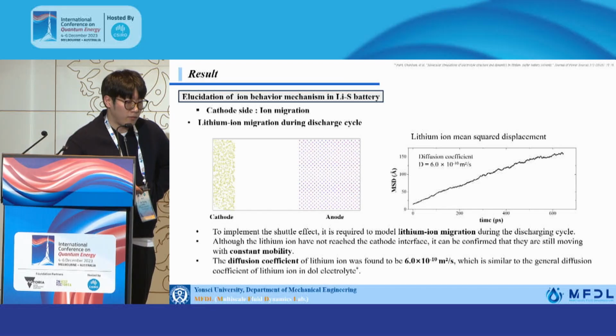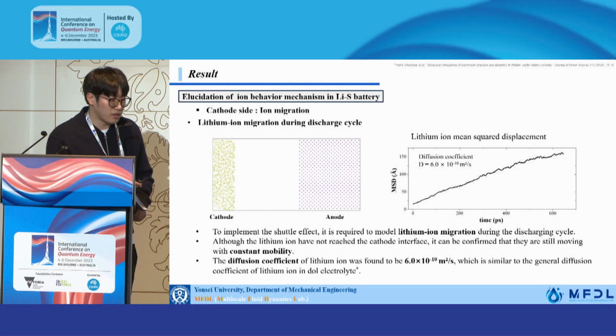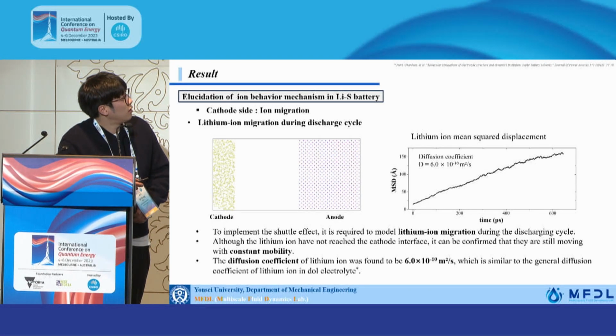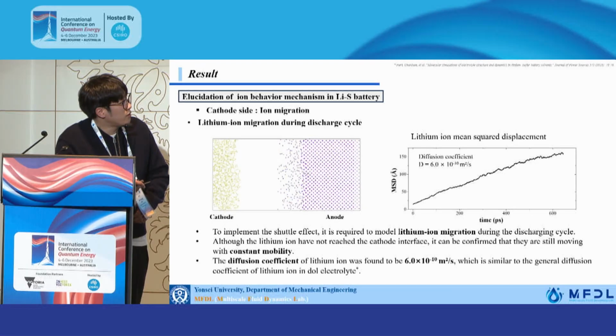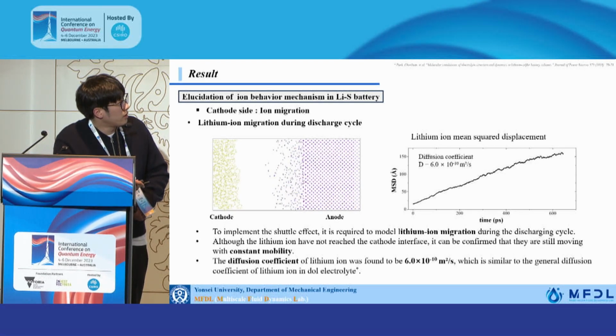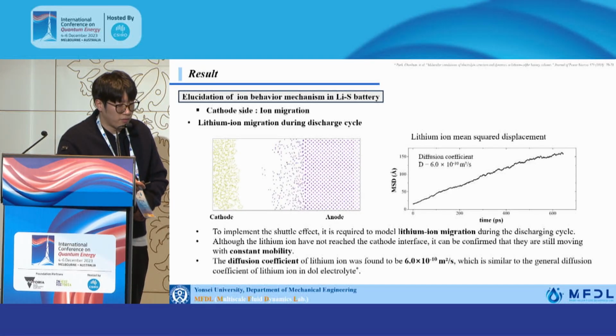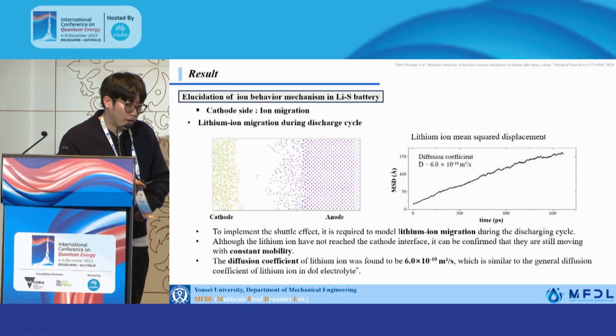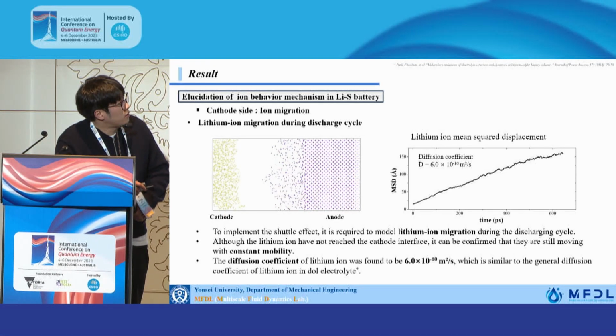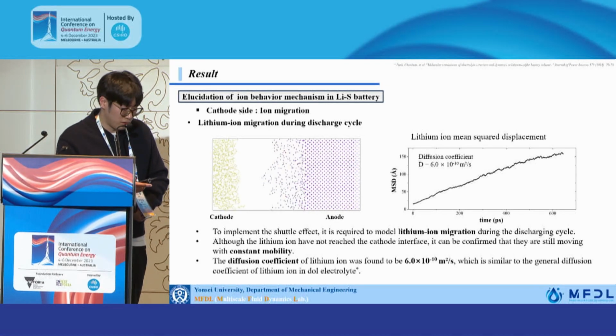And to implement the shuttle effect, it is required to model the lithium ion migration during the discharging cycle. So although the lithium ion have not reached to the cathode interface, we can confirm that they're still moving with the constant mobility. And as we derive the diffusion coefficient of the lithium ion, the value is fit with the previous studies.